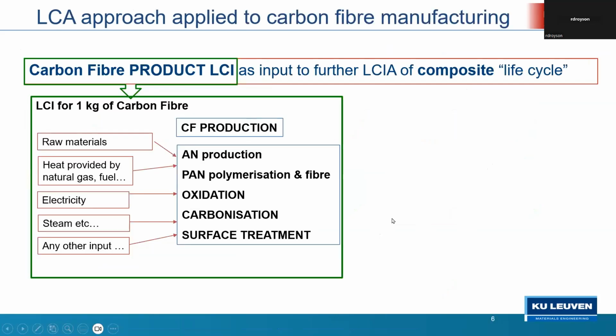Now, for carbon fibers, it's quite straightforward. First, we do a life cycle inventory. That means we do this for the raw materials, for the energy we need by heat or by electricity or steam, and any other input we are using. And then this is what we use as input in the production of carbon fibers. First, we have the acrylonitrile, then the polymerization, the fiber making, oxidation, carbonization, surface treatment. That's what we call the life cycle inventory for 1 kilogram of carbon fiber.